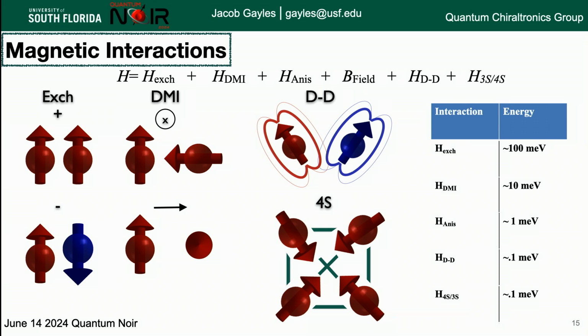Then the DMI, if you break inversion symmetry and you have spin-orbit coupling, it's usually around 10 meV. And anisotropy is usually a bit lower, but it can be on the same size as DMI in interface materials and two-layer materials. And then you have dipole-dipole, which is usually very small but very long range. And lastly, you have these 4-spin interactions, which are usually small, except for when you have large magnetic moments.